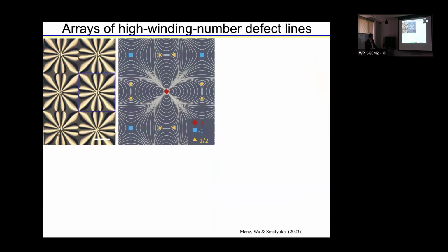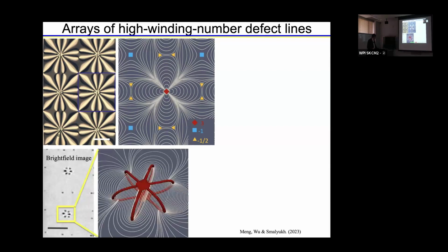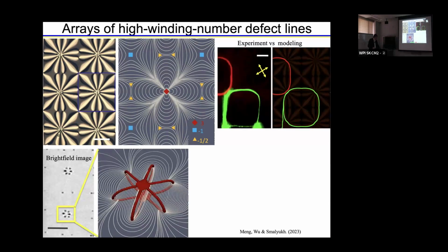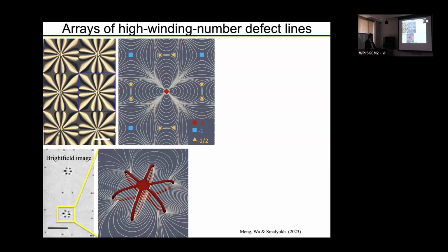In this case, we patterned lattices that have +3 vortices, -1 and -1/2, right? Shown in here in this array. So this is a numerical visualization of the actual structures seen here between cross polarizers. And very interestingly, when I look at these structures in bright field microscopy without cross polarizers, I see that in the center of the +3 object, I actually have 6 dark spots.